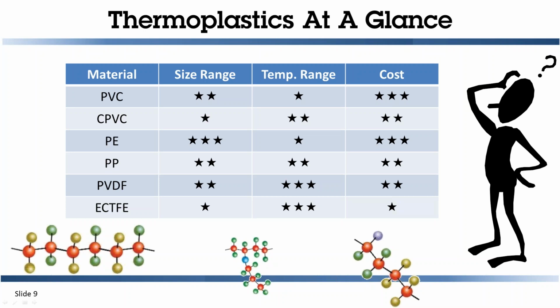PVDF is a very high molecular weight fluoropolymer. It has superior abrasion resistance, dielectric properties, and mechanical strength. These characteristics are maintained over a temperature range from below freezing to 250 F. In piping systems, PVDF is highly resistant to wet and dry chlorine, most strong acids, aromatics, alcohols, and chlorinated solvents. Because it has extremely low amounts of extractables, PVDF is widely used in transport of ultra-pure water for semiconductor and pharmaceutical applications.